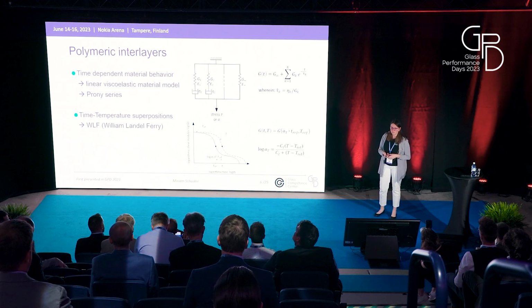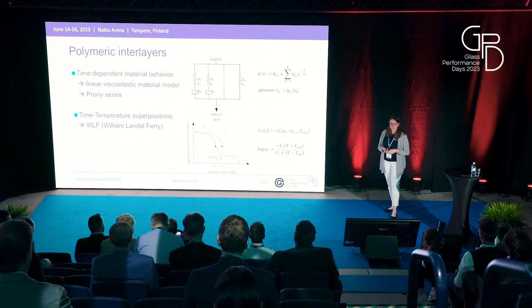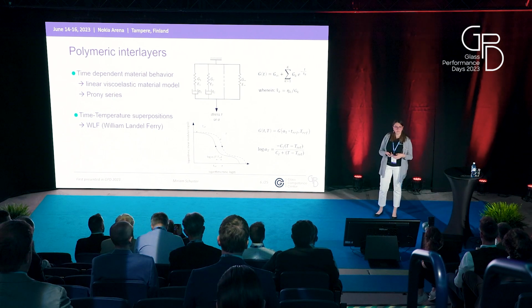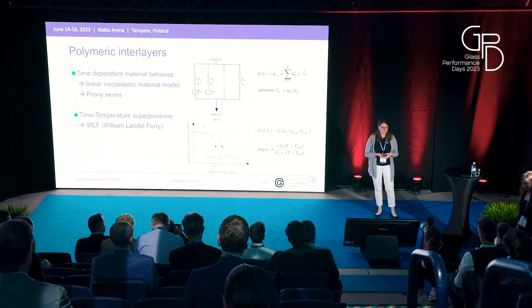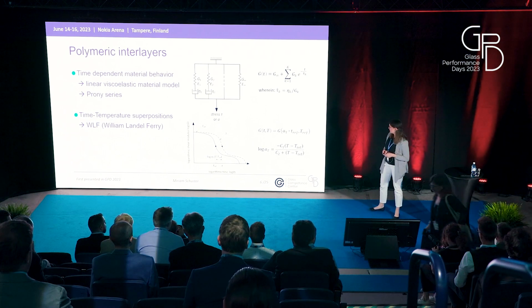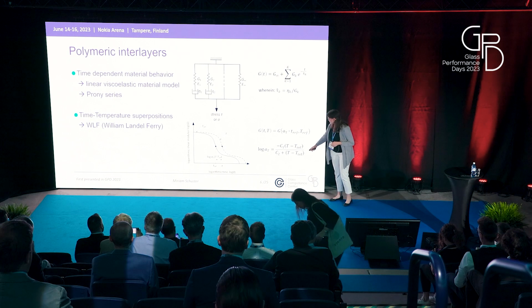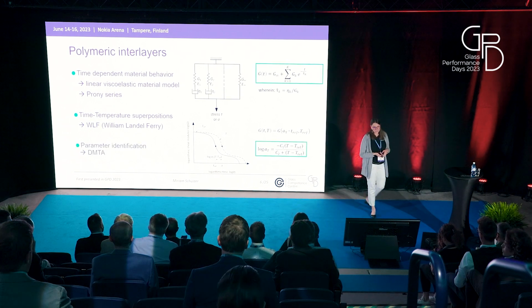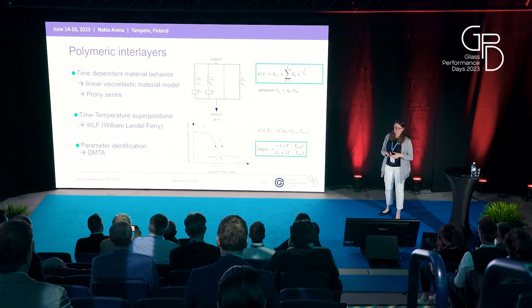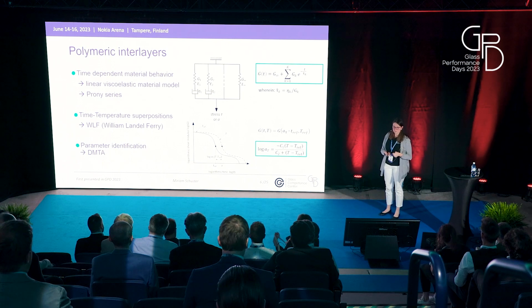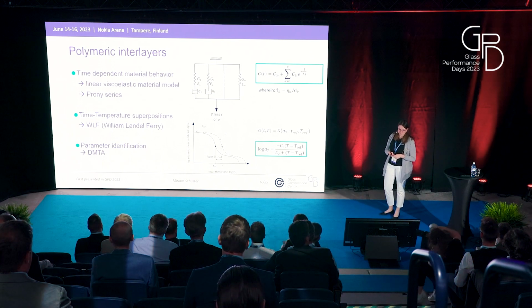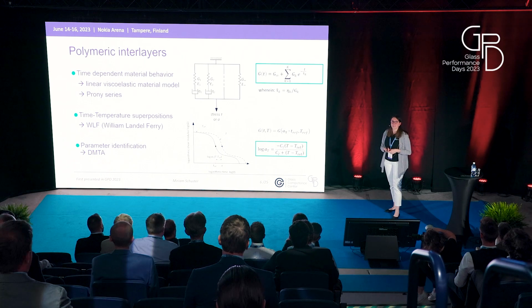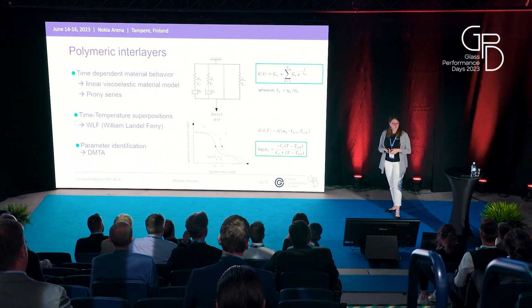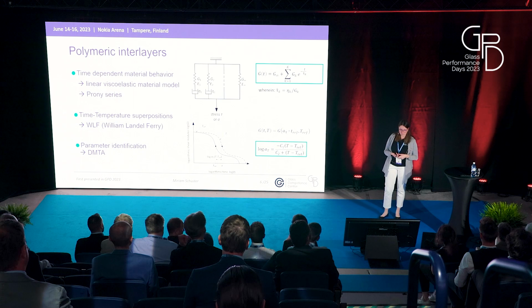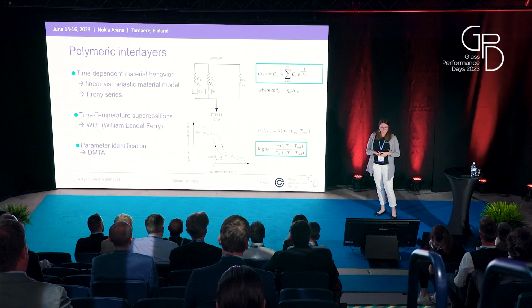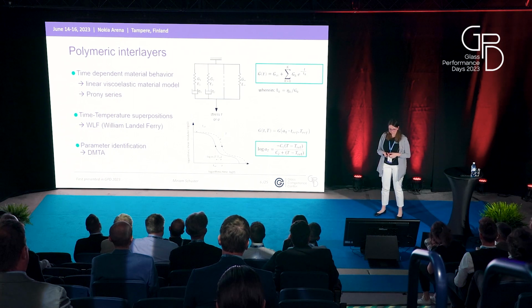And those temperature-dependent shift factors can also be described with some models, and one of the most common models is the WLF model, which is shown here. And now, in order to find the material parameters, which are then the Prony parameters and the time-temperature superposition principle, we need to do some tests. And the most common tests to identify those parameters are dynamic mechanical thermal analysis, short DMTA tests.